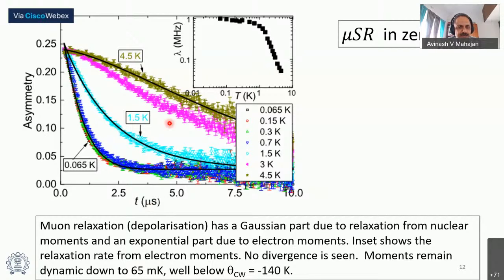And as a function of time, because of the local environment inside, they get depolarized, they lose their magnetic polarization. Here, in the high temperature, due to nuclear moments, but as you come down in temperature, they get relaxed because of the electron moments, so the copper moments in this case. And based on this, you can obtain some kind of relaxation rate for these muons.